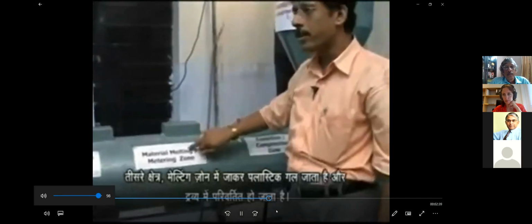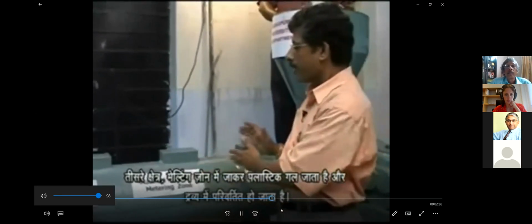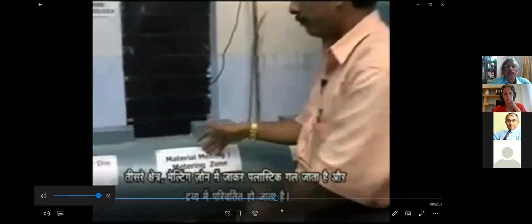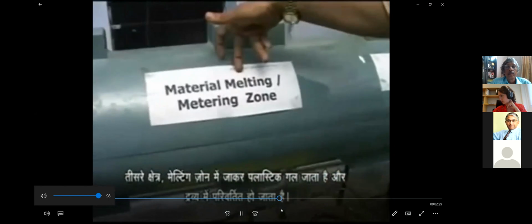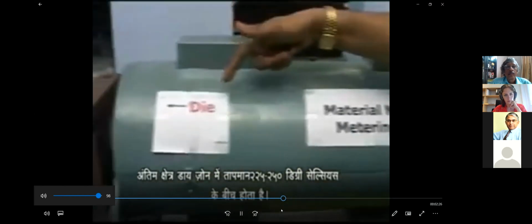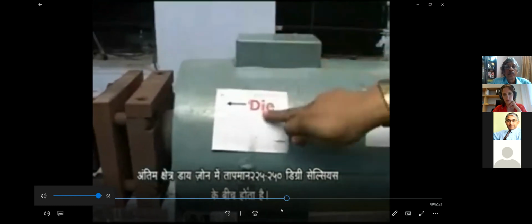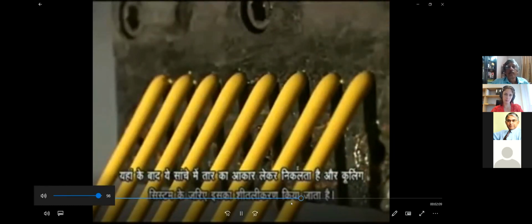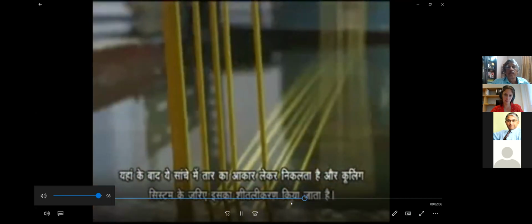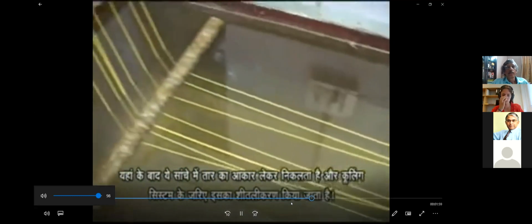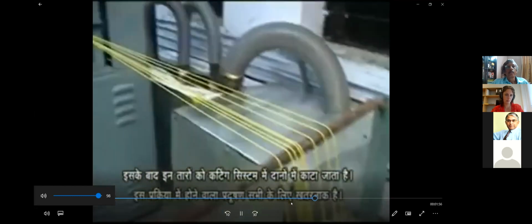And this material goes to the melting zone or metering zone. This is the transition part, where the material goes to the liquid stage. Now, through this liquid stage, the temperature rises to 225 to 250 degrees centigrade in the die zone. Now, this die zone gets the material in melted condition, and through this breaker plate, it goes to the die itself. Now, you can see that the whole die divides the material flow into 8 circular cross sections. It can vary, you can have 6 or 10. Now this material goes through this cooling system to the cutting unit, from where we are getting the granules.